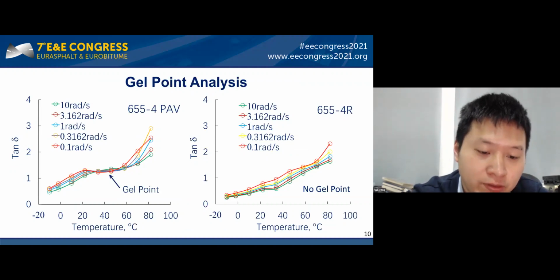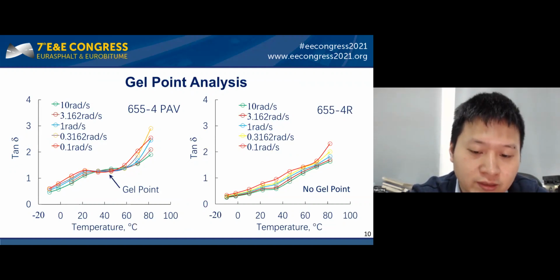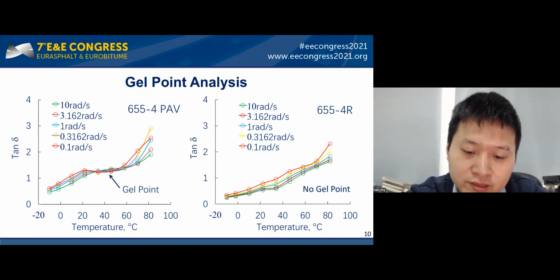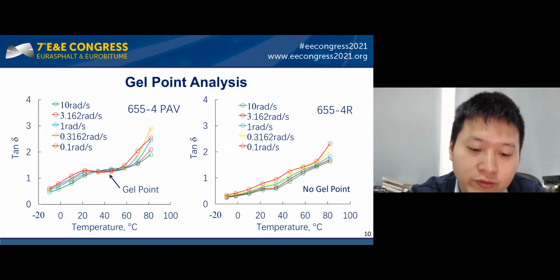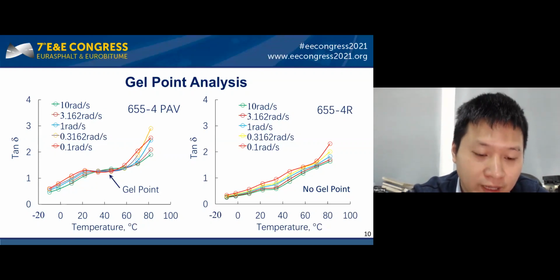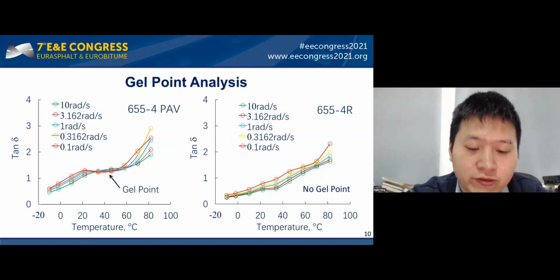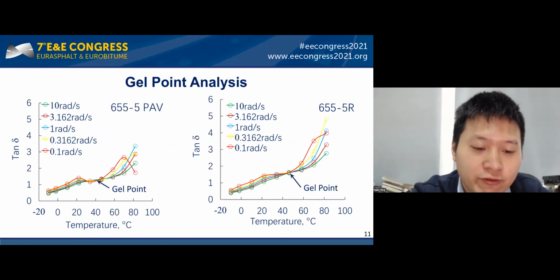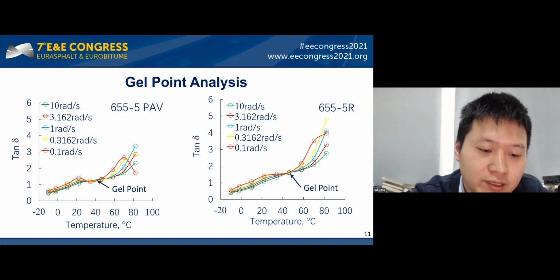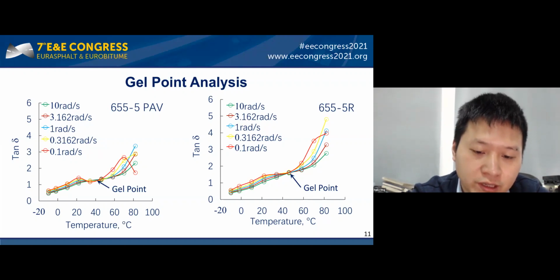We have tested the samples for their gel point, which is rheologically defined by the Chambon-Winter criterion, which states that the tan delta is independent of the frequency at the gel point. For the 6554 binder, the gel point is quite clear in the PAV residue, but disappeared after only a few years of service. For binder 6555, which has a high vinyl content, the backbone of the polymer remains intact and the gel point is still visible after many years of service. However, because the base binder was not of good enough quality, this section also cracked quite severely at an early age.